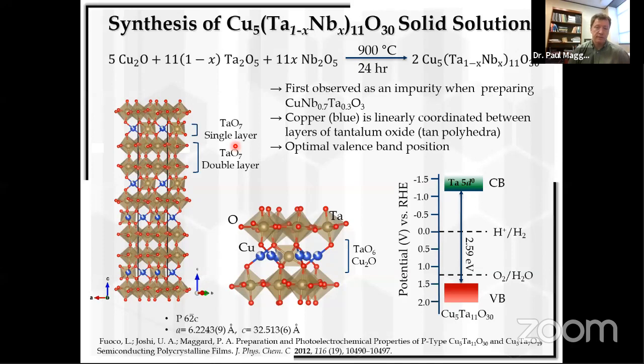And so think of it this way. I described the 51130 phase before, okay? And in that case, it was all tantalum. You can make that same phase now with putting in more and more niobium on the tantalum site, such that the crystalline structure has a distribution of both tantalum and niobium on the same site. You may think, well, what could that do? Okay, and this was a very unusual situation that led to a surprising result, which I'll describe.